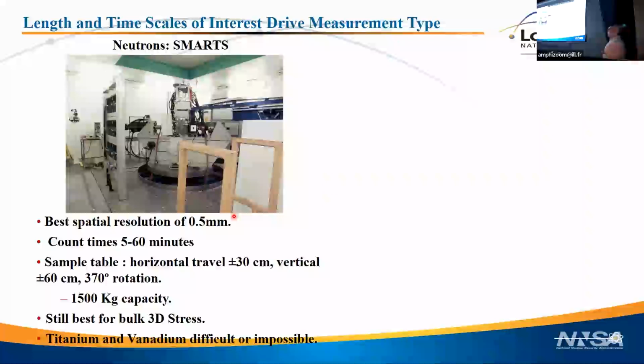Now, I certainly don't want to get into who's better, neutrons or X-rays. You folks know that as well or better than I do. I will go through some of the valid points that matter, though. Neutrons, that's a picture of my instrument, SMARTS. So I list here best spatial resolution of 0.5 millimeter. It's true that I can do a measurement with 0.5 millimeter resolution. It takes me 6 hours to get one diffraction pattern. That's actually something I can do now that I'm mission focused. I'm not paper focused. That allows me the leeway to do that. But in reality, almost 90% of the time, our best resolution is 2 millimeters, not 0.5 millimeter.